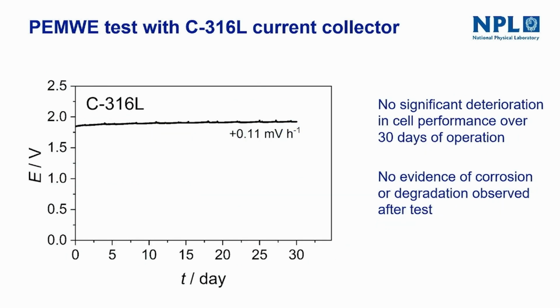We also ran a longer 30-day test, this time with no reference electrode, just to take a look at the carbon-coated stainless steel at the end of the test, and it showed that there was no corrosion or evidence of degradation, whereas anyone who had ever set up a test before but put the carbon in contact with the electrode, it just disappears in seconds.